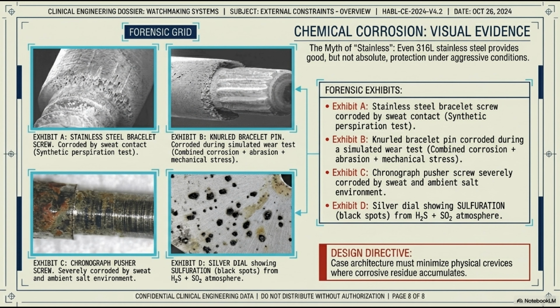Look at the forensic grid on the screen. This is visual evidence of chemical corrosion on what we call stainless steel. The myth of stainless is precisely that, a myth. Grade 316L stainless steel provides excellent, but not absolute, protection under aggressive conditions. Look at Exhibit A. This is a solid stainless steel bracelet screw. It has been severely corroded, eaten away simply by prolonged contact with human sweat during a synthetic perspiration test. Exhibit B shows a knurled bracelet pin. The combination of sweat corrosion, abrasive grit, and continuous mechanical bending stress has utterly destroyed the steel matrix.